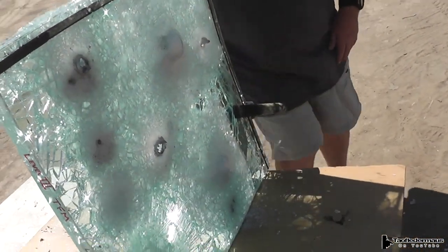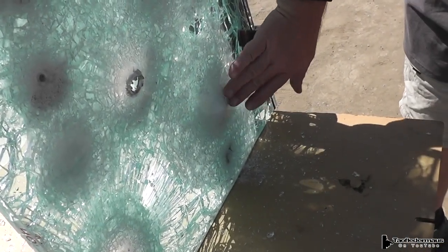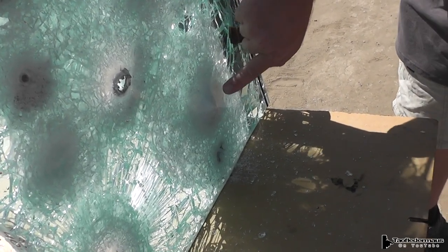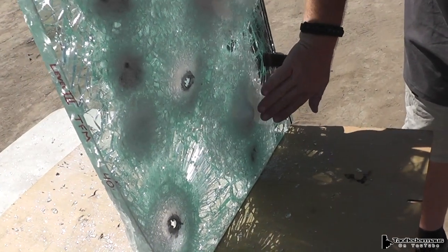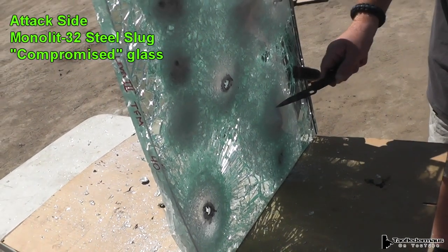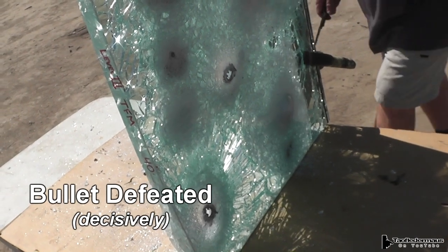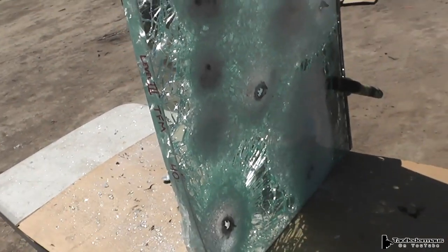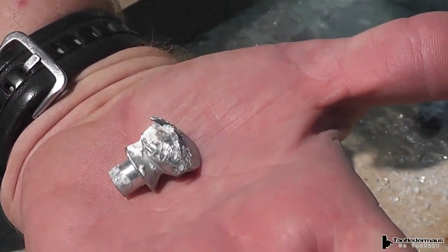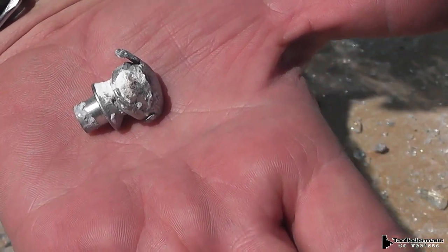It's got to be inside there — but it stopped it too. Look at that. You've got a little bulge right there. That's amazing. Less of a bulge than the last one. A huge difference just from shooting it with the attack side toward the shooter. Perfectly smooth on the back. Fantastic. And that was very compromised glass too. We found the slug about five yards away — a deformed chunk of steel on the ground. It hit the glass and bounced back out.